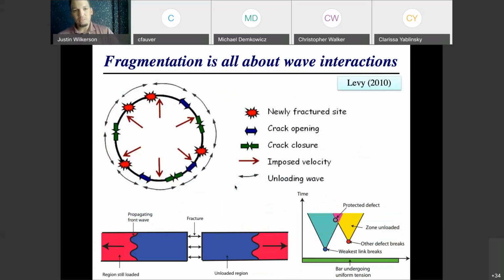The last, I'll just briefly say for fragmentation, fragmentation is really about a competition between elastic wave propagation causing release waves to release a material point before it gets to fracture. So I don't think I have time to do this justice, but essentially just think about the fact that as you're loading, let's say that we're expanding this ring here, and we're expanding it outwards at some constant velocity.